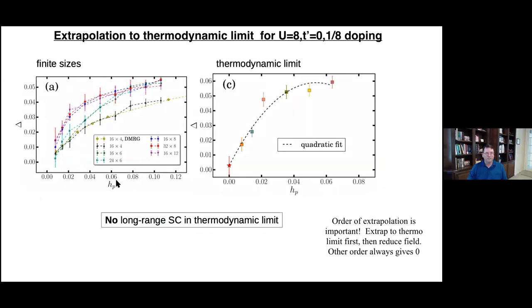So what you need to do is, for a fixed value of the field, you have to take the thermodynamic limit. And then the final extrapolation shown here is extrapolating with the field, where each point is in the thermodynamic limit. And if you do the limits in the opposite way, you'll just always get zero no matter what the quantity is. So here we extrapolate essentially to zero.